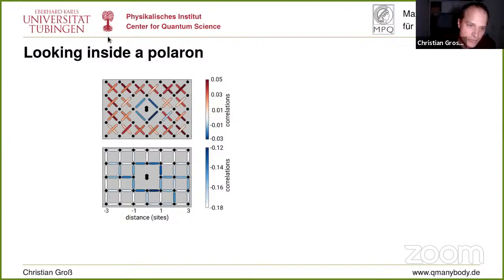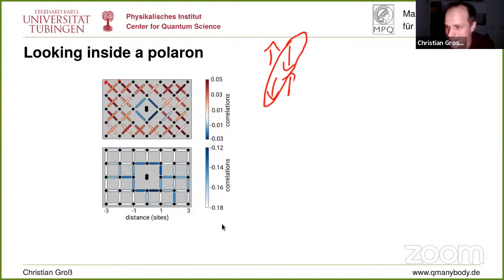So first of all, what I show you here in these plots is that the black dots are the positions of the atoms, and the bar is the magnetic bond strength. And if it's positive, it is ferromagnetic, like aligned. And if it's negative, well, it's anti-aligned, right? So if we look at the diagonal bond in such an antiferromagnetic model, if it's fully filled, you see it's aligned. And this is what we see if we go far away from the position of the doublon. But you see near the doublon, we actually get a flipped correlation here. So the doublon really messes up the spin, and it messes it up so much on this diagonal correlator that the correlation flips completely compared to the doublon not being there.